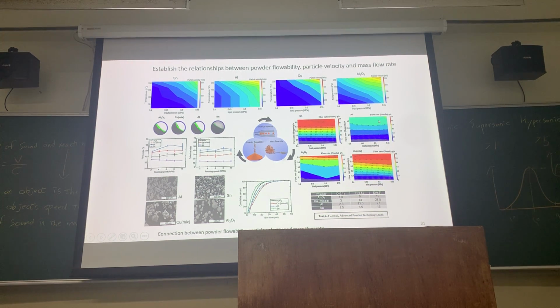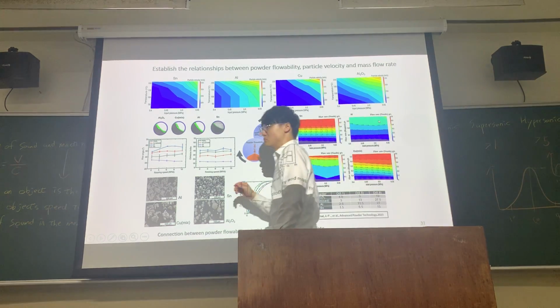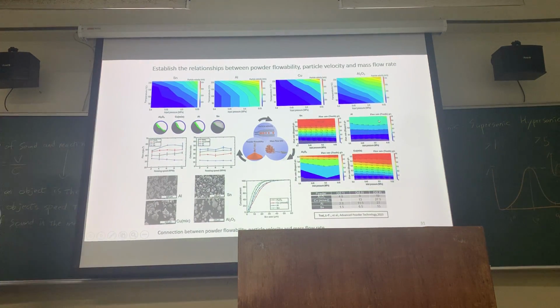And if you just look at the 10, 50, and 90%, it's going to give you 50% over here, and then 10% over here, and then 90% over here. Okay, so I think it's very deceiving when you just read these numbers. It's always good to plot the numbers out. So be careful when you read the papers.